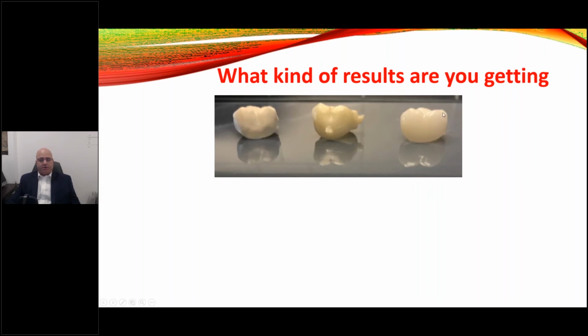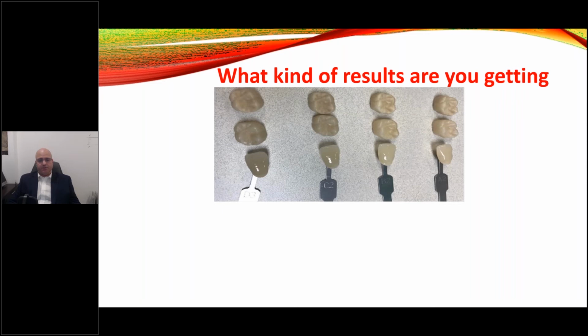And obviously you see the one all the way on the right is the one with the true proper sintering parameter. This one, as you can see here, was sintered at a higher temperature than need be. And then this one is on too low of a temperature, and you see that it's very opaque and looks almost unaccomplished. Now, it's the same design, the same mill, the same puck, just fired at different sintering intervals, and therefore provides, as you can see, completely different results. Notice here what a 20-degree difference makes.